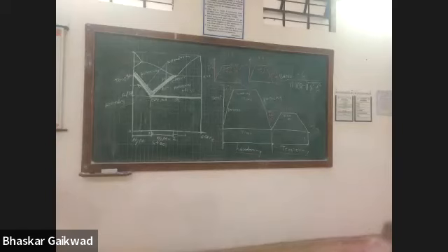To avoid such bending or distortion, you can change the quenching media. You can go for oil quenching. If you face problems in oil quenching also, then you can go for air quenching. And if air quenching also has the problem, then the component has a certain problem in the design itself, so you need to change the design of that component.